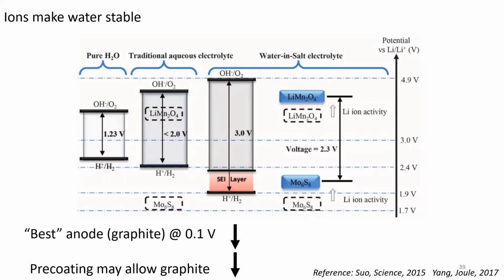They made a prototype battery. They had to use molybdenum sulfide as their anode, lithium manganese oxide as the cathode, and they ran at like 2.3 volts. That's not that close to the 3.8 volts that's in our commercial batteries, but it was a big paradigm change for, hey, we can consider water. One thing to note is that we're looking at voltages that are quite high compared to our best anode, which is graphite with lithium in it, which is down at 0.1 volts.